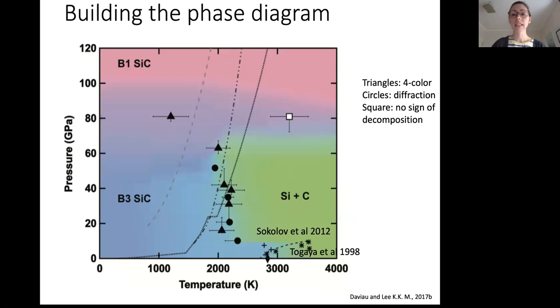Right, so if we put all of this together onto a pressure-temperature phase diagram, we have the previous data, which is down below 10 GPa from Sokolov and Togaya. And then our data are these solid symbols here. The circles represent the diffraction where we saw the appearance of carbon diamond in the sample. And then the triangles are where we observed that change in the optical characterization in the four-color heating system. And so they're really well correlated, meaning that these two separate observations are likely corresponding to this same melting breakup of silicon carbide, the point where carbon begins to come out of this silicon carbide.